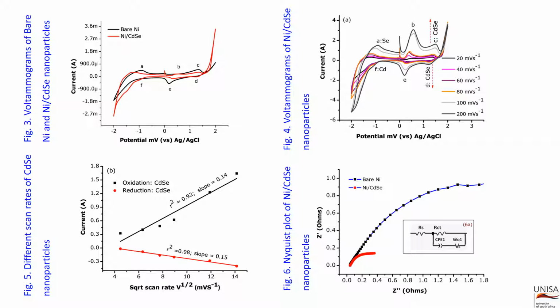Figure 5 suggests an effective use of the modified electrode with the electrolyte owing to better ionic diffusion due to the quantum confinement of the material. In figure 5, parameters such as the diffusion coefficient D and the surface coverage were determined. For convenience, only the results from the reduction peak currents are reported.